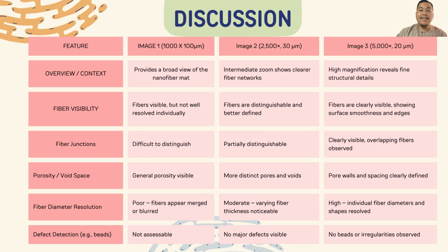In summary, as the magnification increases, the resolution of the fiber morphology improves. At 1000, we get a general overview. At 2500, we can observe individual fiber networks. At 5000, we get precise morphological details for quantitative analysis. This SEM image confirms that the nanofiber mat has a uniform, bead-free structure with random fiber orientation and good porosity, making it suitable for applications such as filtration or biomedical scaffolds.